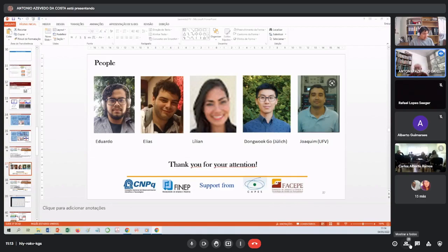This was also proposed theoretically in the 2018 theoretical paper that I have shown, authored by this guy here, Dongwook Go. He also proposed that if we use tantalum or tungsten instead of platinum, the phenomenon should decrease, because the coupling between L and S is negative. The coupling between L and S in platinum is positive, but in tantalum it is negative.